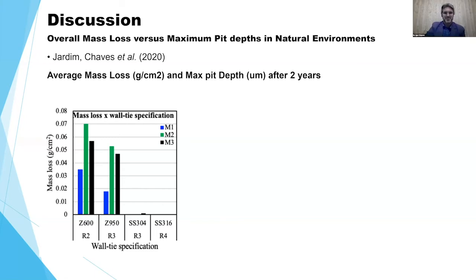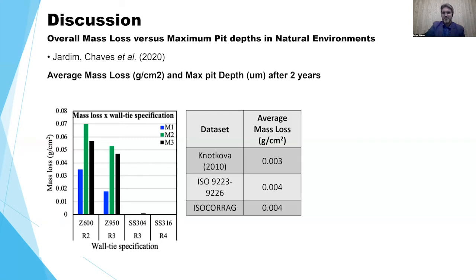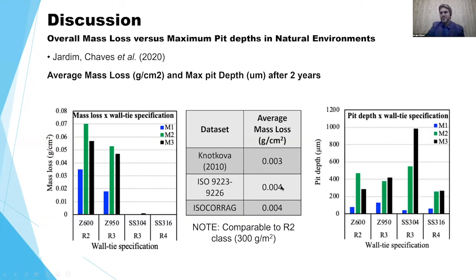So as you can see here in the mass losses, we have mass losses versus wall ties comparing the galvanized to the stainless steel. So overall mass loss of the stainless steel is almost negligible compared to the galvanized. And compared to the previous model's predictions, the mass loss results we are obtaining are orders of magnitude higher compared to the previous model's prediction. So there's something going on there. And we're comparing this to the R2 class here, yeah? So 0.02 compared to 0.003 or 4. The pit depths, on the other hand, is quite relatable between any type of material. So it really just depends on what sort of corrosion mechanisms take place at a particular wall at a particular time.